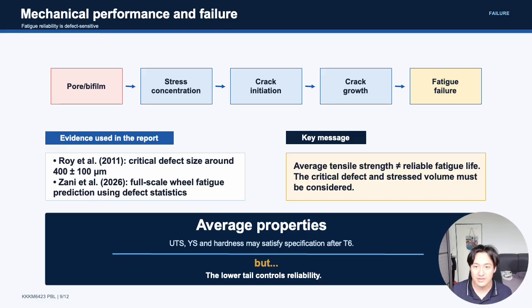Mechanical performance should include the strength, ductility, and fatigue. T6 has increased the strength, but fatigue often starts from the defects at stress levels below the monotonic yield strength. The Kitagawa-Takahashi diagram and S-N curves show that the defect size changes the endurance limit in A356-T6. Similar curves extend this idea to full-scale wheels using the defect statistics and local stress analysis. This is why component reliability cannot be judged from average tensile strength alone.